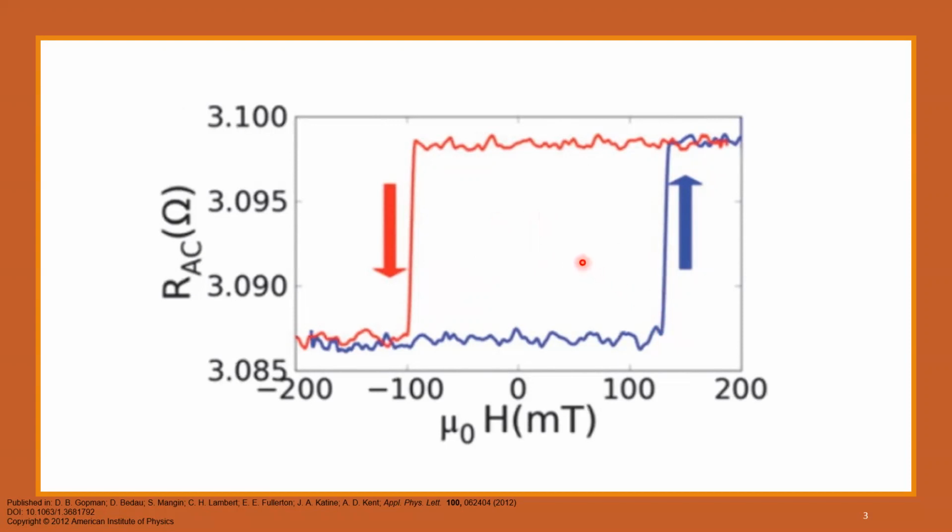However, the field from the polarizer can change by more than 100% from edges to center. Therefore, the inhomogeneous dipolar field from the polarizer can play a larger role than can be described by a single dipole field. So to investigate the effect of the inhomogeneous dipolar field, we should address it through the study of the statistics of the magnetization reversal process.